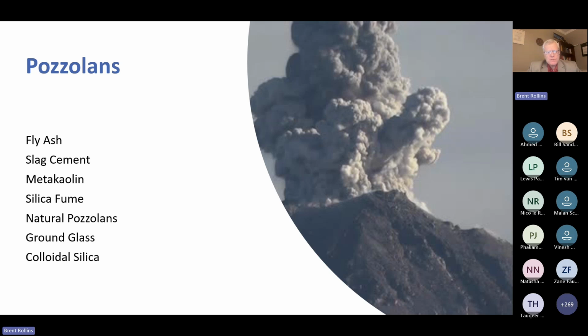I think we still have quite a bit to go through, but it's caused us to start looking at other pozzolans. And all of these other pozzolans that you see are supplementary cementitious materials. I use those terms interchangeably. They're not exactly the same, but the word pozzolan comes from that volcanic ash that the Romans called pozzolana. So when we rediscovered that pozzolanic activity, we sort of Americanized the word and called it pozzolan instead of pozzolana because pozzolan's a little easier to say.